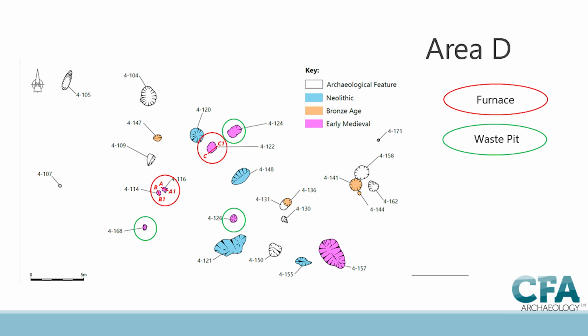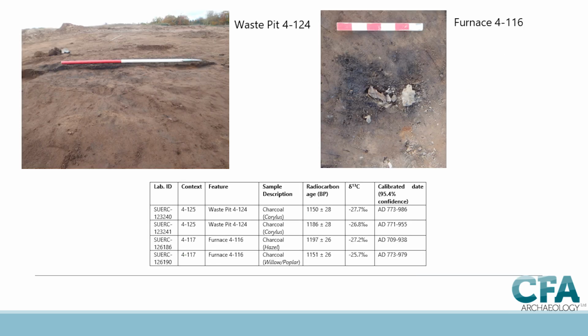Having a look at the ironworking furnaces, as you can see, they're not quite spectacular. They are quite shallow features. This could be due to the truncation, and they are relatively small. And so they were almost ignored on site, not ignored, but recorded and written about and reported. But it was only due to the radiocarbon dates that they were actually indicated as being early medieval. They were thought to be post-medieval dumpings of slag material. So actually it shows the importance of dating some of these features.